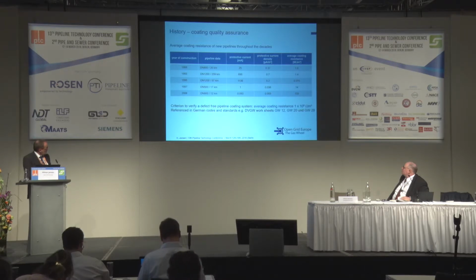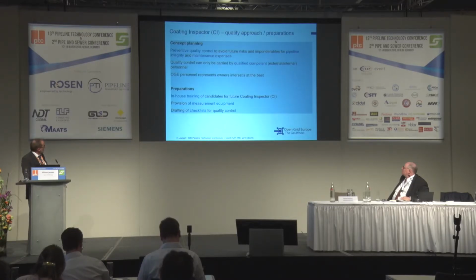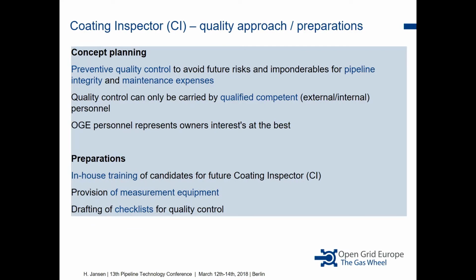With this fixed threshold value, we could again increase the average coating resistance, which is our benchmark figure in measuring the coating quality. So we then asked one day, everything is perfect, we have certified people who apply the systems in the field, we have certified material that is tested by DIN, that is tested by DVGW, but the only puzzle that is missing in the system is the quality of the system on site. And so we started to give some concept planning.